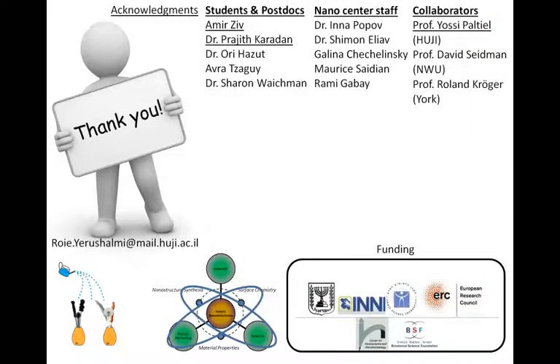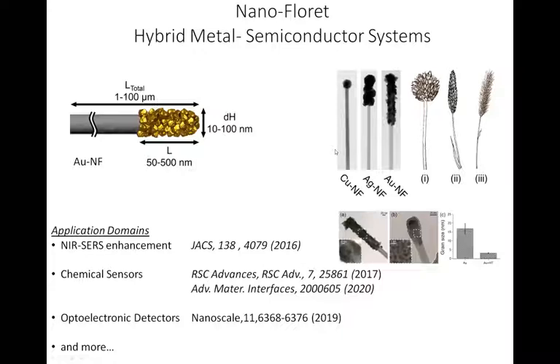Thank you all. So with that, let's go directly into the interesting stuff, where these nanoflorets are basically, as I said, nanowires, which we modify with specific chemistry that occurs at the tip of the nanowire, where from the CVD growth, we have the gold catalyst, which changes locally the redox and chemical potential of the components, and therefore we are able to have this copper, silver, and gold, as I showed, nanoflorets, and we can further fine-tune the structure of the tip itself by adding, for example, thiols to the deposition solution.